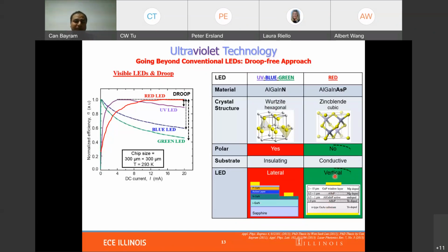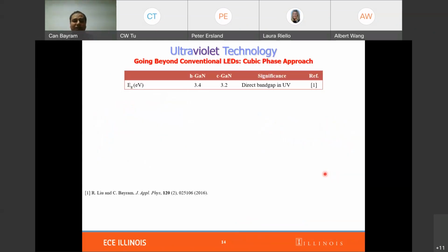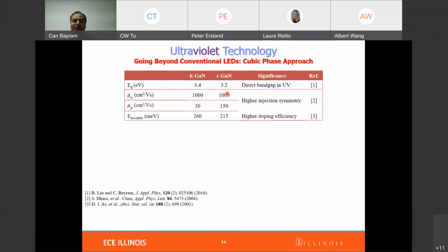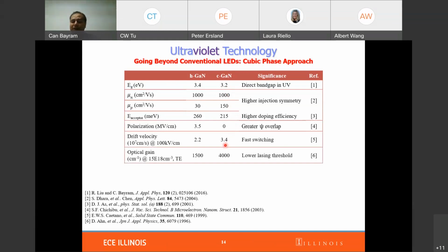So in the future, why not use this know-how and create non-polar vertical UV, blue, green LEDs. Now, one way of doing this is switching the material phase from hexagonal six-fold symmetry to cubic four-fold gallium nitride, a high symmetry system. So the band gap of cubic nitride is 3.2, and it's a direct band gap. It has much better mobility values, higher symmetry, and lower activation energy. So you can achieve higher injection, higher doping efficiency, higher overlap integral because of the non-polar nature, and higher drift velocity, ideal for devices, and higher optical gain, lower laser threshold.